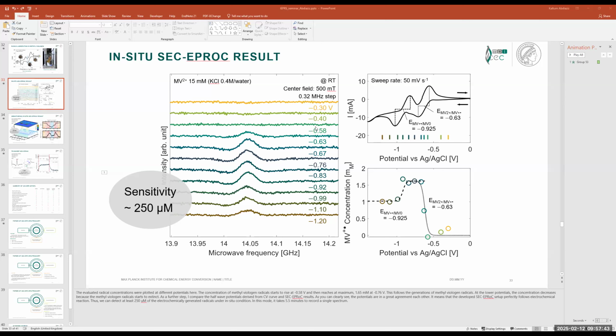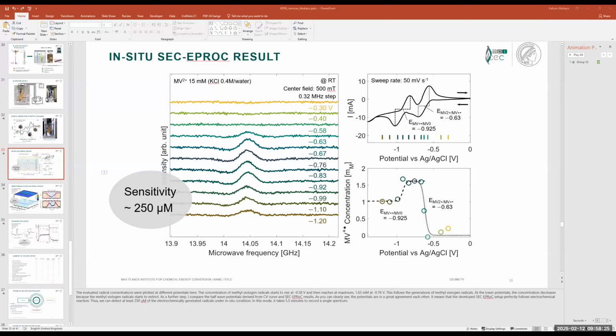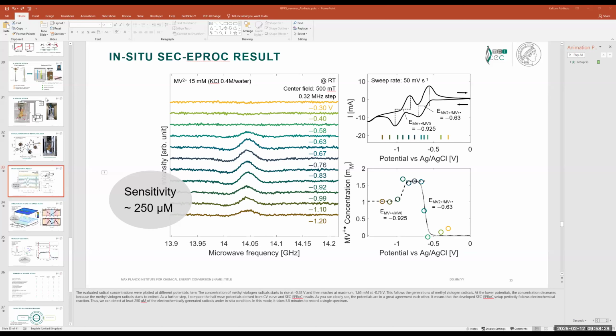The other thing I was going to ask you is, you mentioned drop casting. So back in the day, 2015, when Adam Kinney was working for me, we started doing electrochemical EPR on some of the Dan Nocera catalysts. So we were electrodepositing cobalt phosphate catalysts onto the electrodes. And we did essentially what you did, which is to put them at a potential and then trap them and freeze them and go do the EPR spectroscopy. Have you been able to electrodeposit catalysts so that you can tell at what point in the electrodeposition you make an active water oxidation catalyst? You mentioned drop casting them, but I haven't seen anybody do what we did. We never published it, but I'm wondering why that's so hard. I mean, it was hard for us, but I'm hoping other people have been able to do it.